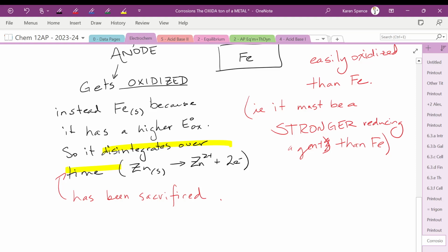The reason iron oxide is such a problem is you end up with flakes, right? And then it peels off and reveals the metal below, and you end up with air bubbles in between the flakes where the water can get in. So that's why iron oxidation is such a big problem, right? It just keeps going and going because it destroys the structure of the top layer. Whereas zinc or something else, just the top layer oxidizes and then you have that oxide and it's flat and nice and stable. Yes?